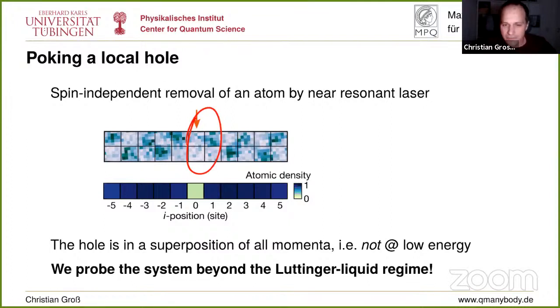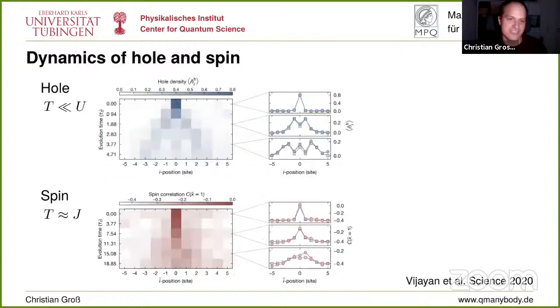Maybe a little comment for the experts. Maybe you have heard that the 1D Fermi-Hubbard model is actually a Luttinger liquid, and that what we are doing here is not studying the system in the Luttinger liquid regime, because Luttinger liquid is all about the low k excitations. But when you kill an atom on an individual site, that is intrinsically a very high k excitation. It's fully localized, right? A very high k excitation in the system.